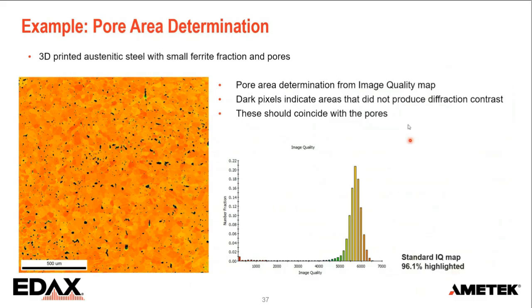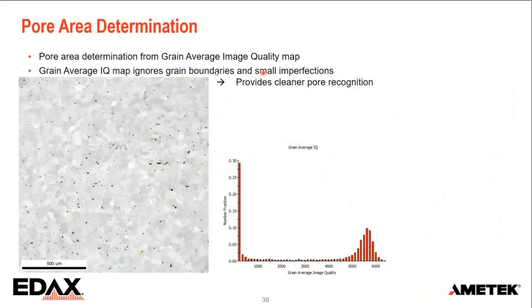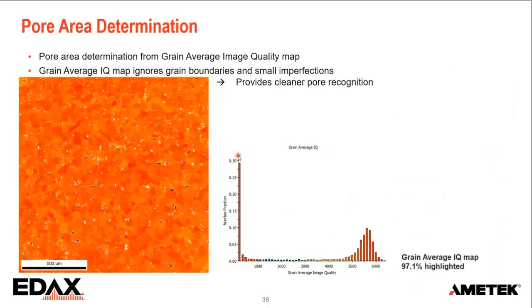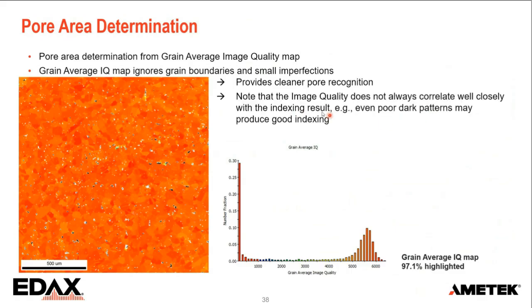Now, this is something I don't really like to do because grain boundaries may also have very low IQ. So instead, I can go for a grain average IQ. So I remove all the dark lines at boundaries. And now you can see that the very poor image quality values is much less than what we had before. So I can do a highlighting again. Now it's 97.1% highlighted. So it gives me a cleaner definition. But still, with IQ, it's very sensitive also to polishing. You have to be a bit careful.